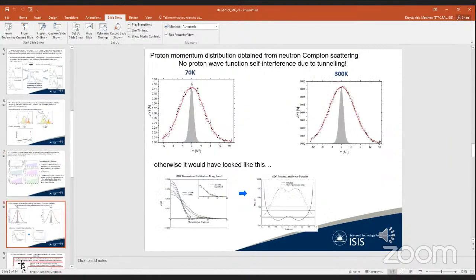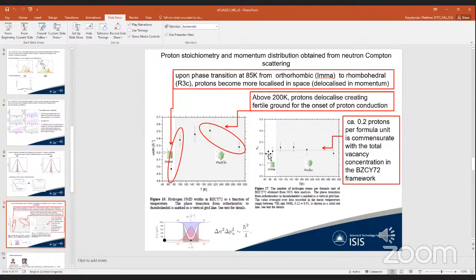We can also measure the proton momentum distribution function, which is a square of its wave function. And it is Gaussian, which means that the mechanism of proton conduction is classical. So we have classical hopping instead of coherent tunneling across the hydrogen bond. Moreover, we can plot the stoichiometry, the number of hydrogen atoms per formula unit as a function of temperature, and it is constant, 0.2 protons per formula unit, which is commensurate with the total vacancy concentration as predicted by literature.